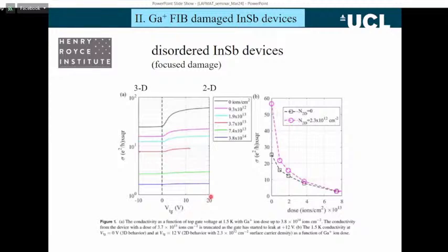So at positive gate voltage and no damage, that's the black line here. We go from a 2D region, we're dominated by the 2D region at the surface, back down to a 3D region. So as we change the gate voltage, we have charge at the surface, and then we just have this 3D region in the bulk, in the disordered bulk. Then as we introduce ion beam damage, so this is gallium ion damage, as we put more damage in, the conductance drops down, and eventually we just lose this surface. We lose this high mobility on the surface.